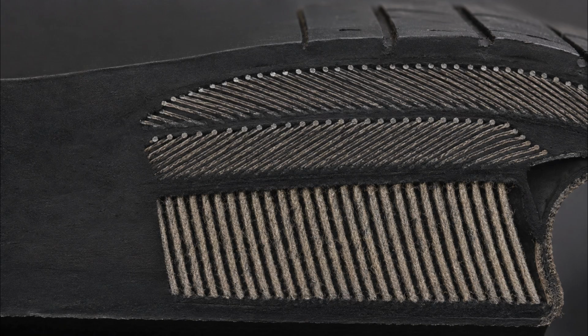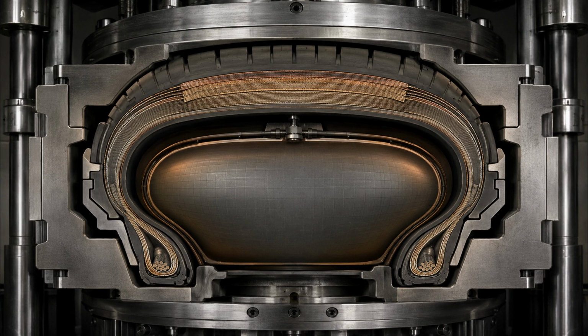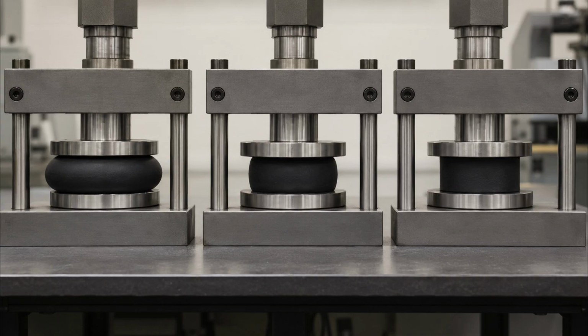Inside, the rubber heat activates the chemical system prepared in the mixing room. Cross links form between polymer chains, limiting how freely those chains can slide. The soft compounds become resilient elastomers. They can deform under load and then recover instead of remaining permanently distorted. The steel belts do not melt into the rubber. The textile cords do not disappear. Each material remains structurally distinct. Curing creates the rubber network and bonds that allow all of them to function together.